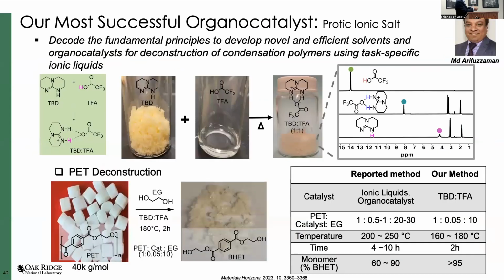And one signature, okay, it's a little hidden there, but Arif, he's here. He did excellent work. So we developed an exciting and excellent catalyst. This is the best catalyst right now. Although it's simple, this is a strong base, this mixture TBD-TFA, nicely mixed. This is much more efficient than existing ones. So this case is PET, plastic bottle material. We can cook it, and then you get ethylene glycolysis. With conventional materials, you require much more catalyst. It takes much longer, higher temperature. Now it's only 5% more, around 180 C, 2 hours, you get quite high yield.